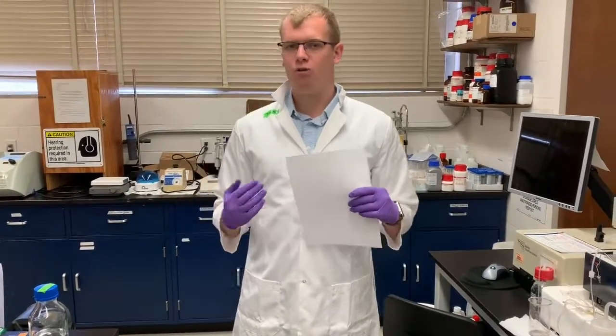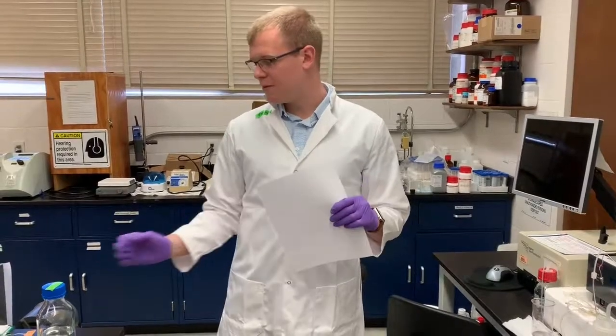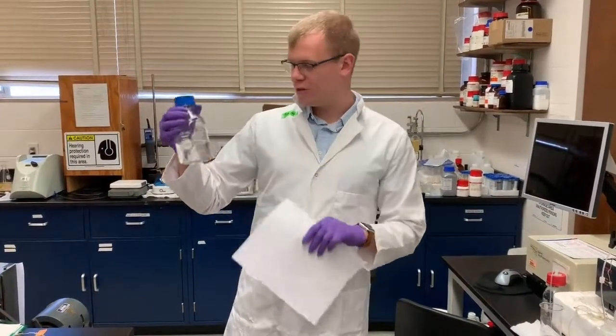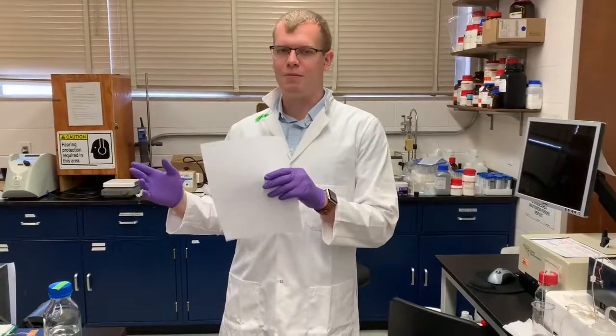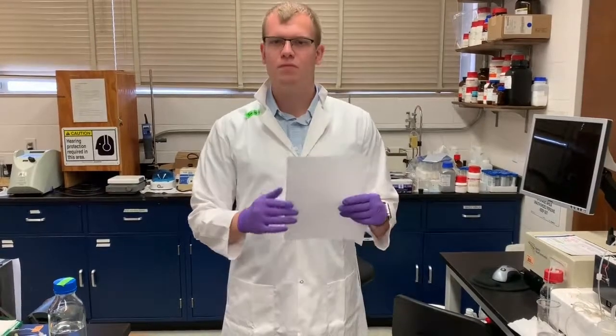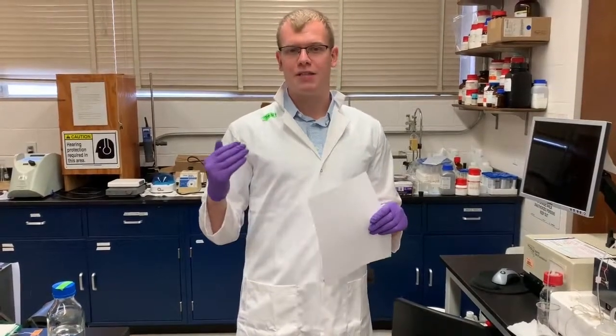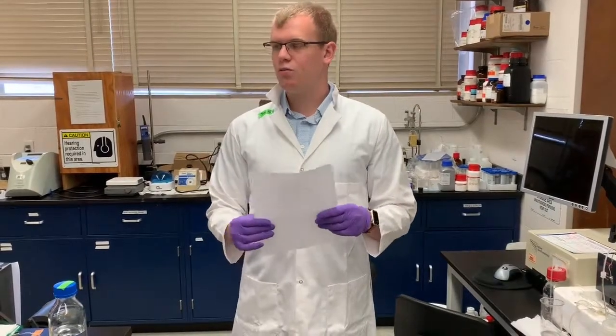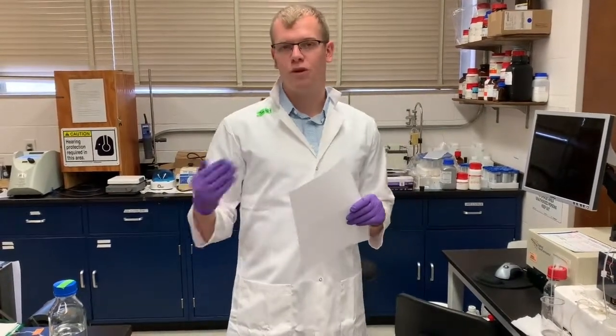Our research group here at Ziegler Lab has been using polyNIPAM hydrogels, which here are a couple of them dissolved in solution. PolyNIPAM at around 32 degrees Celsius transitions from a hydrophilic dominant state, so it really likes water, to one that doesn't like water, and it pushes all its water out. So if you were to trap a drug inside of polyNIPAM and then have it transition from its water liking stage to its water hating phase, it would push the drug out with it. That would be a much more efficient method because you can control when to release it.